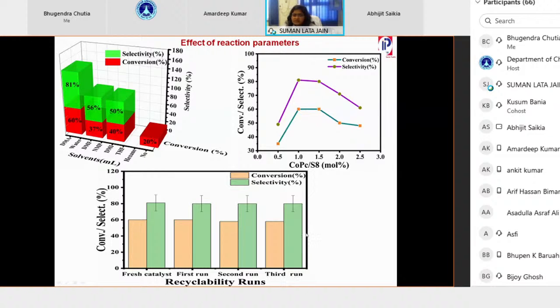Similarly, these are the recyclability data. We can see that this is the fresh catalyst and this is the third run. The recovered catalyst we used for the third run. So in all the cases, we obtained consistent selectivity and conversion. So we concluded that a very low amount of catalyst is enough for the maximum conversion, and the catalyst was nicely stable. We did not find any degradation of the catalyst, and it could be easily recovered and recycled up to 3 or 4 runs without any significant decrease in the activity.